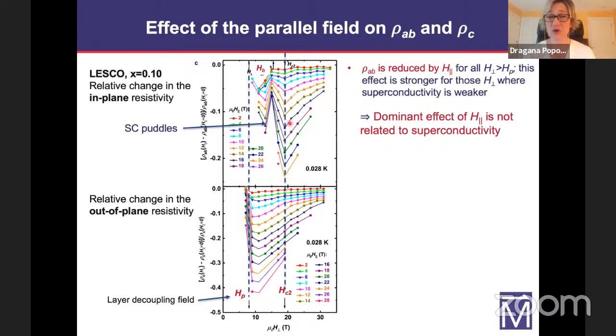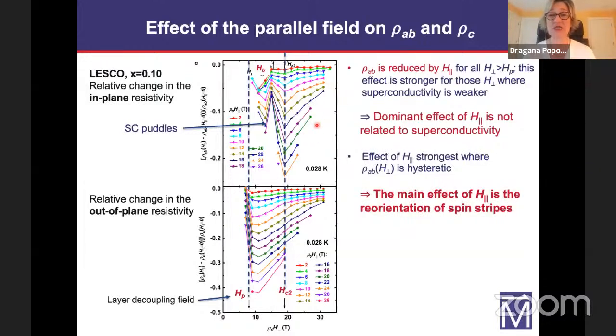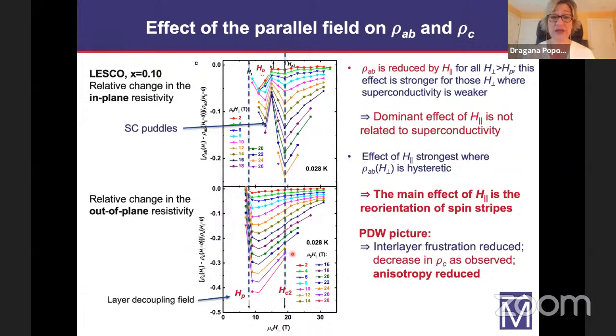And in fact, it's most pronounced in the regions where we observe some hysteretic behavior in the magnetoresistance that I didn't have time to discuss, but which is consistent with the presence of domains of spin stripes. So we conclude that the dominant effect of the parallel magnetic field is the reorientation of the spin stripes. In that case, one expects, as I said already several times, that the frustration of the interlayer Josephson coupling will be reduced within the pair density wave picture. We should see a reduced out-of-plane resistance, and this is exactly what we see. And the effect on the out-of-plane resistance is stronger, so the overall anisotropy is reduced.